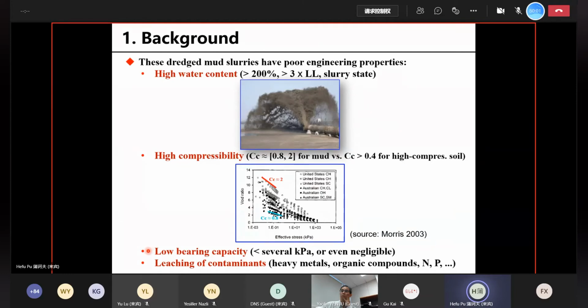And also because of its high water content, it has very low bearing capacity. Usually the bearing capacity is lower than several kPa, usually lower than 2, and sometimes even negligible, and cannot be measured using conventional testing equipment. And also because of uncontrolled release of polluted water into the aquatic environment, more and more frequently those mud slurries contain contaminants. For example, heavy metals, organic compounds, or nutrients such as nitrate or phosphorus and others.